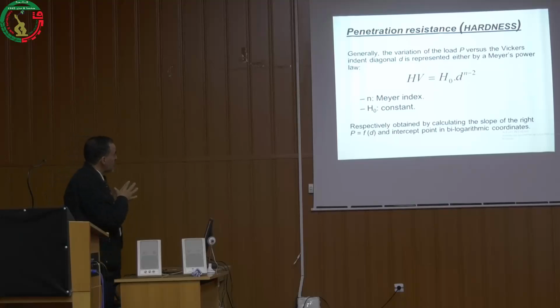Here we are concerned with calculating the n, which represents the Meyer index. Or we can use another formula by replacing the HV with P, the load, and d to the exponent n, not n minus 2, but d to the exponent n.